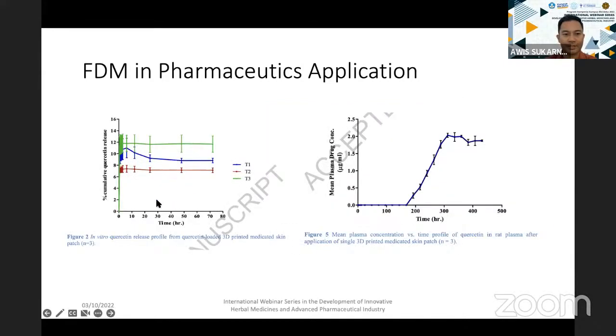And then from here you can see the in vitro study. The patch showed like a constant release up to 70 hours. You can see the release is quite consistent, except for the T1 formulation, where they showed a quite high release profile at the beginning, and after that it starts to release at a constant rate.